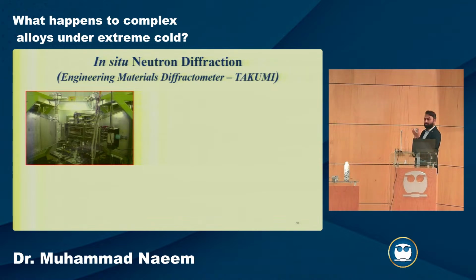Now going to the instrument which we use. In this case, you see that there is this huge machine, but it is on a sample table. On top of that is the loading machine, which we use for cryogenic experiments. And on two sides of it, you see this conical kind of structure. These are the detectors. And the neutrons come from the back of this machine. They interact with the sample, and then they are scattered towards these two detectors. Because there are two sets of detectors, we can get behavior along the loading direction when you're pulling the sample, for example, and also transverse to that direction.